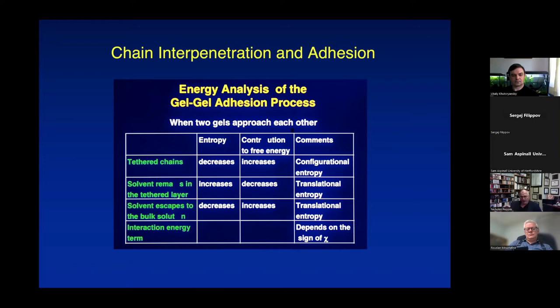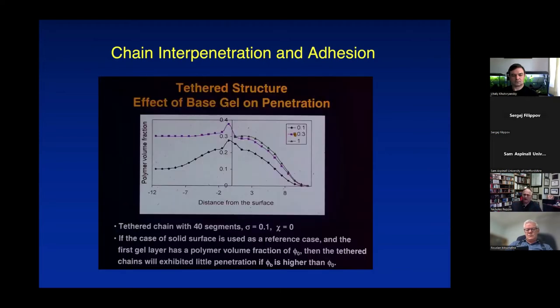What about a solvent that was in the hydrogel, in the material, and now it's being pushed out? That will decrease the entropy. You see, anything that will provide order will change the entropy. And we are able to calculate all these things, including the dependence of the so-called chi factor. For those of you who are not polymer scientists, the chi factor is a compatibility parameter that tells you how thermodynamically good the polymer is with respect to the surrounding fluid.